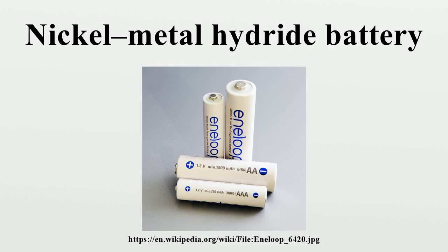Delta V charging method. In order to prevent cell damage, fast chargers must terminate the charge cycle before overcharging occurs. One method is to monitor the change of voltage with time. When the battery is fully charged, the voltage across its terminals drops slightly. The charger can detect this and stop charging. This method is often used with nickel-cadmium cells, which display a large voltage drop at full charge. However, the voltage drop is much less pronounced for NiMH and can be non-existent at low charge rates, which can make the approach unreliable. Another option is to monitor the change of voltage with respect to time and stop when this becomes zero, but this risks premature cutoffs.